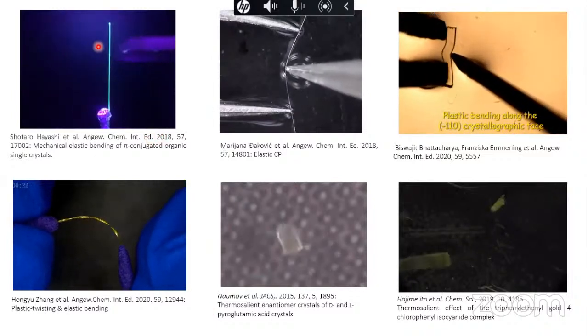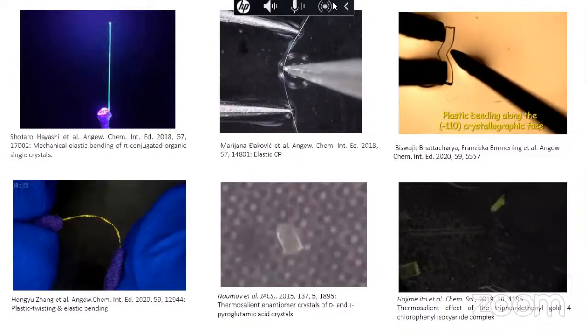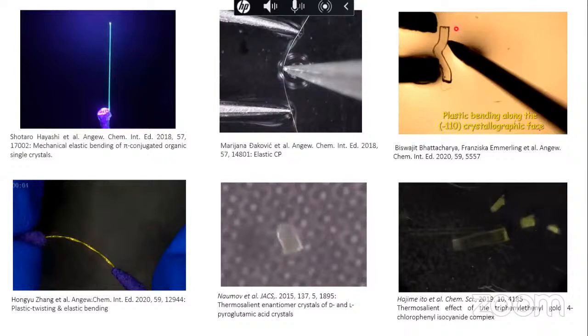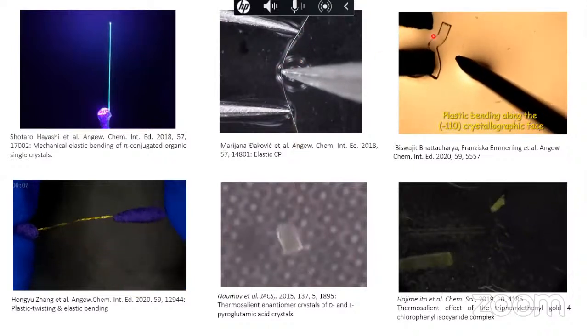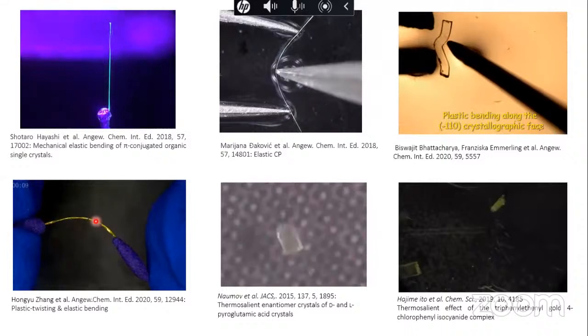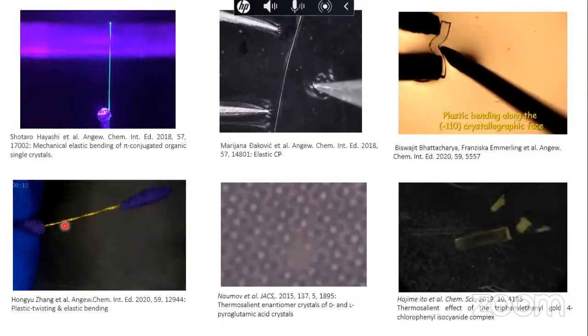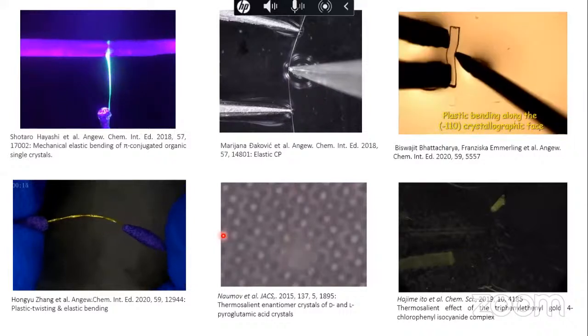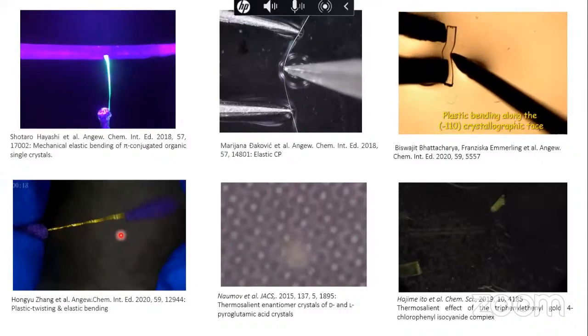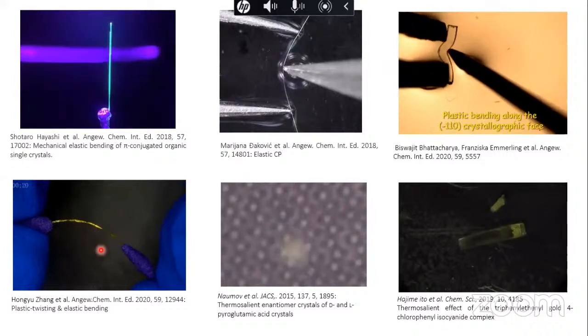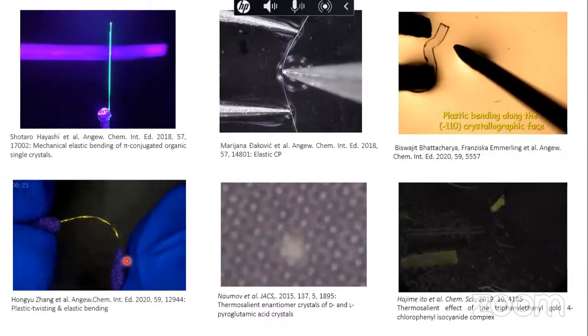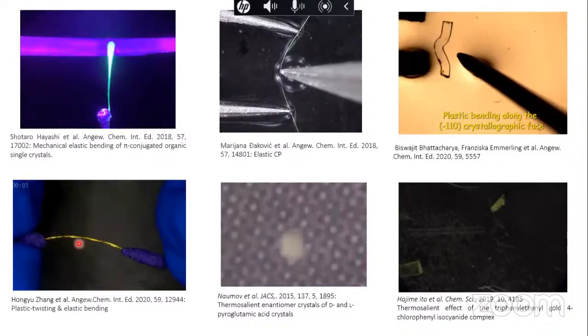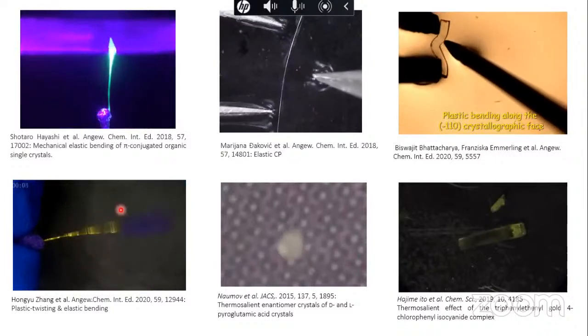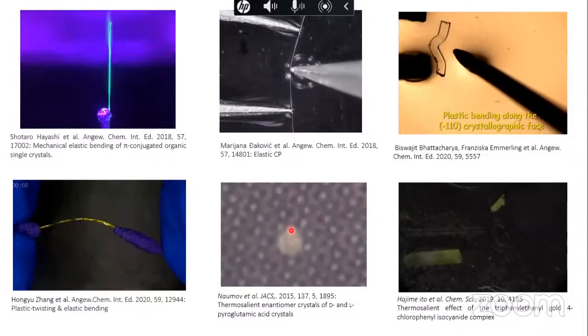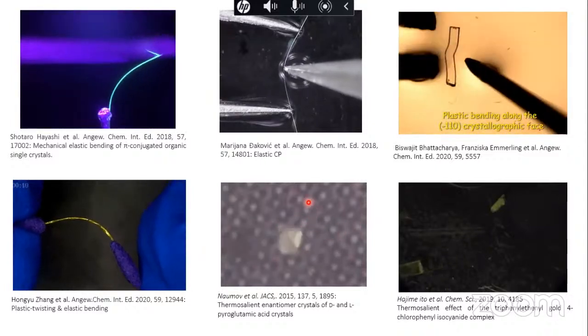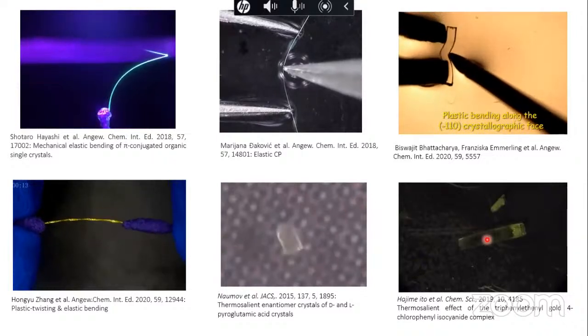And now there are so many examples, and people have been working on different applications and many things. For example, here it's a nice fluorescent crystal, and this is a metal organic complex, and this is also a metal organic complex. It is elastic here, this is plastic, and here the bending is elastic. But there is also a twist. If you see, the crystals are actually twisted, right? The crystal is not unwinding because it is a plastic twisting. Twisting is plastic, that means it doesn't recover, but the crystal can be bent elastically. So this is very interesting, right? Here you have a thermosalient crystal, where you can see that crystals can jump when you hit them, and this is again.